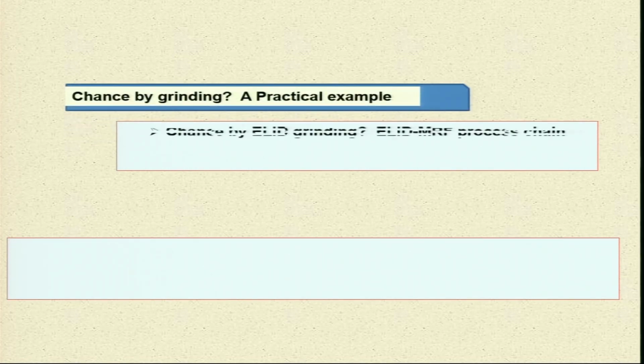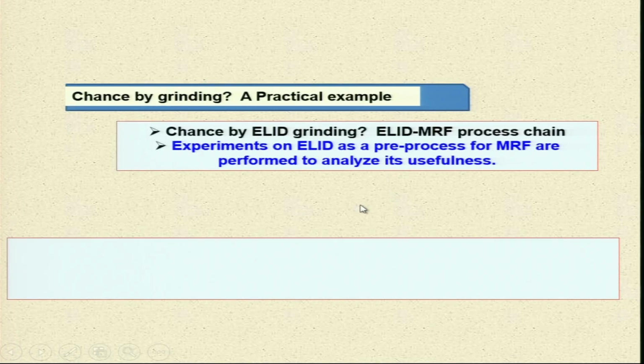Chance by grinding, a practical example. Chance by ELID grinding, ELID-MRF process chain. MRF is magneto-rheological finishing. Here we try to combine both of them, so that you get better results. Experiments on ELID as a pre-process for MRF are performed to analyze its usefulness. That simply means first you perform the ELID, you get a certain surface finish, and after performing the ELID process you go for the MRF, magneto-rheological finishing, which gives you better surface finish after grinding.